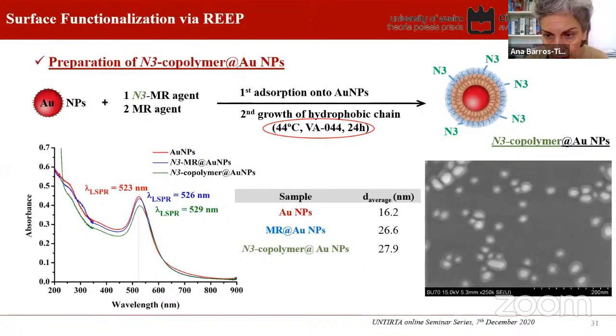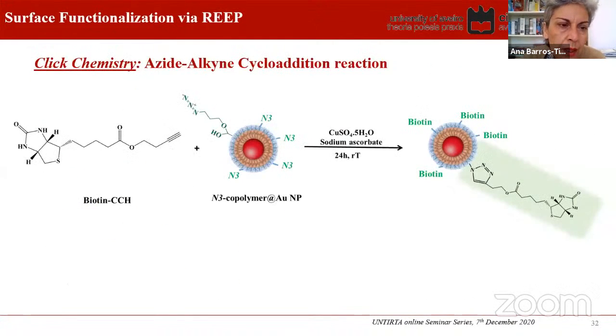But anyway, it just slowed down to a certain extent the polymerization reaction, but allowed the preparation of these functionalized gold nanoparticles with this azide group, which later, via click chemistry, allowed the anchoring of biotin to the gold nanoparticles.